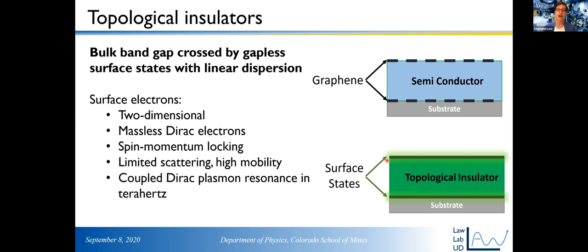What's special about topological insulators and what's different than graphene? So what's the same as graphene? These surface states are two-dimensional, just like graphene. They have massless electrons, just like graphene. The electrons travel at a substantial fraction of the speed of light, just like graphene. But unlike graphene, they exhibit spin momentum locking. This means that an electron traveling in the plus X direction will have spin in the minus Y direction. It's just the way it is.